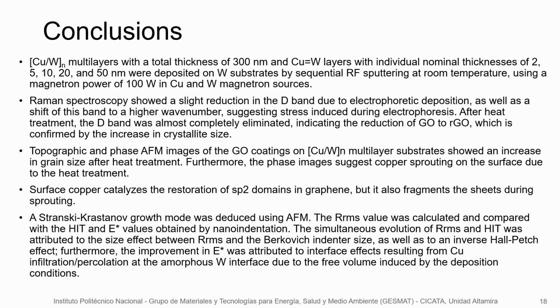Topographic and phase analysis by AFM images of the coatings on the copper-tungsten multilayer substrate showed an increase in the grain size after the heat treatment. Furthermore, the phase image suggests that copper sprouting on the surface due to the heat treatment. Surface copper catalyzed the restoration of sp2 domains in graphene, but it also fragments the sheets during sprouting. Using AFM, the roughness of the sample was calculated.